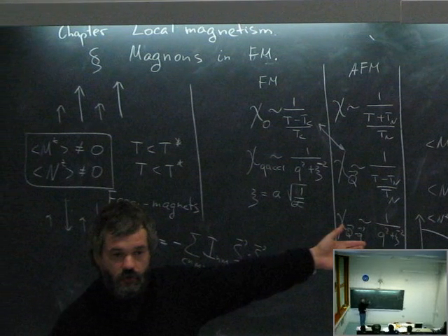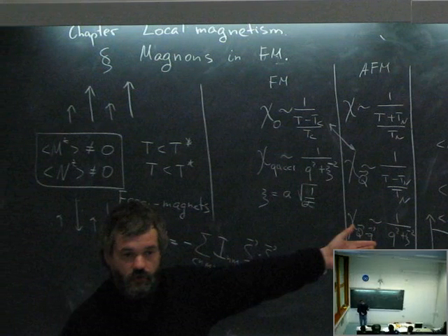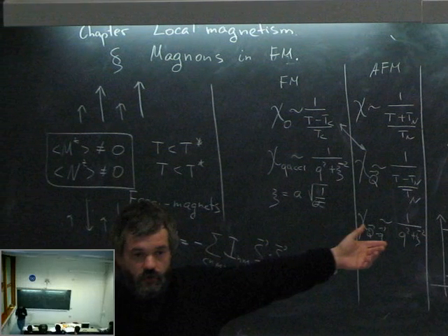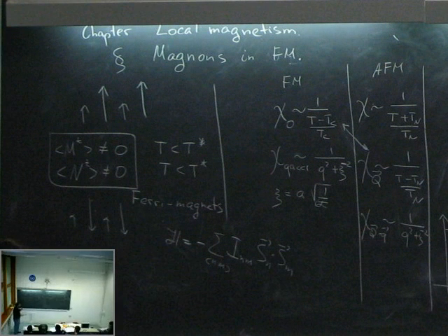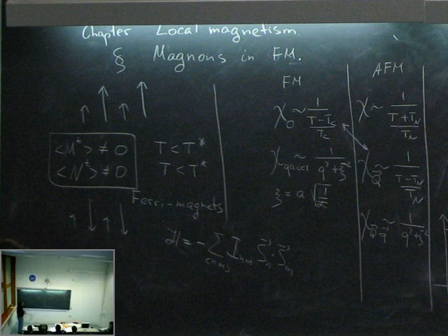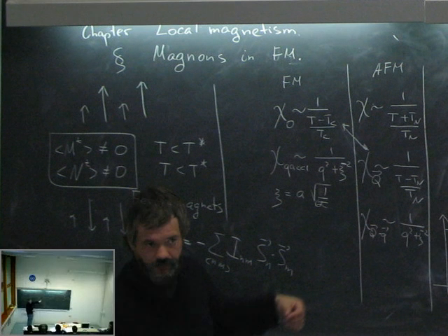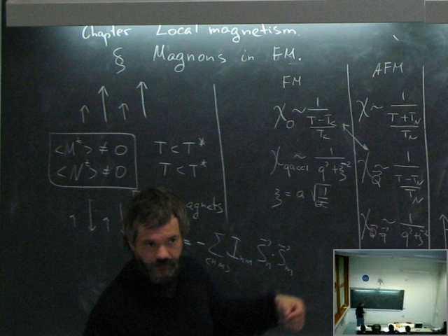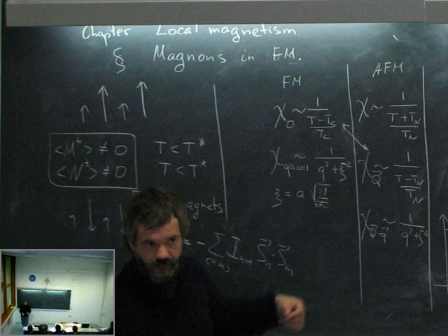And then measuring the diffraction cross-section, you have access to measuring the susceptibility directly, because the cross-section is proportional to the imaginary part of susceptibility as a function of Q and omega. And if we come to the Q and omega frame, in the simplest approximation, this imaginary part will be just a sum of delta functions. And if you see that your susceptibility is peaked at zero momentum, it's an indication that you are working with a ferromagnet, and therefore there is one sublattice.